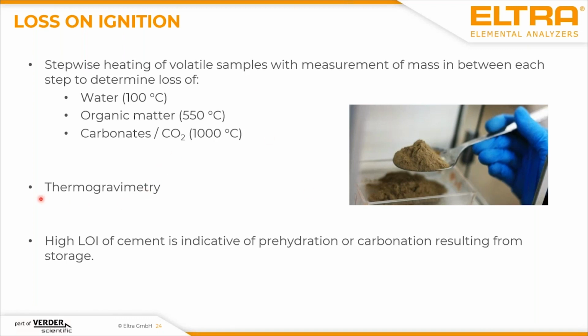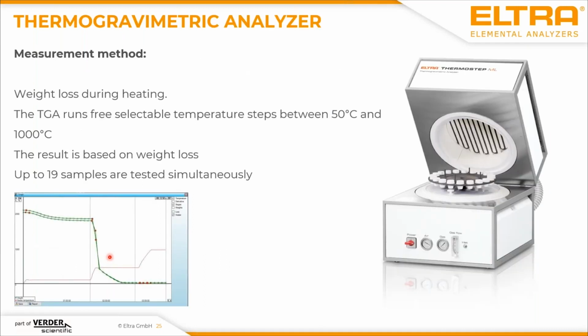And this is done by thermogravimetry, which means that we have an instrument which has a furnace and a balance. We will see on the next slide. And for example, here you see, if you have a high loss on ignition, if the mass loss during this heating process is high, which means that you have a high value of moisture or prehydration or carbonation in your sample or in your storage. On the next slide, we see how such an instrument looks like.